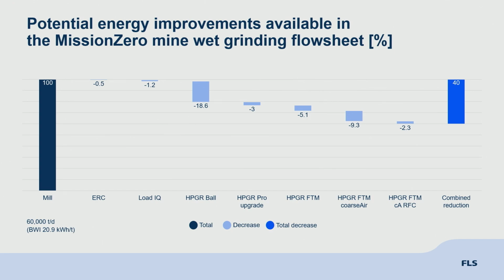So that was great. So we looked at this, and then we looked at our coarse flotation. So we had to change to a coarser grind. We changed from a 150 grind, sorry if this is getting technical for some people, a 150 P80 to a 350 grind. But that means we had to rerun the whole thing in our SysCAD simulation model. And once we reran that and moved the grind size, we got a further 9.3% reduction. And then if you took out conventional flotation, you got another 2.3%.